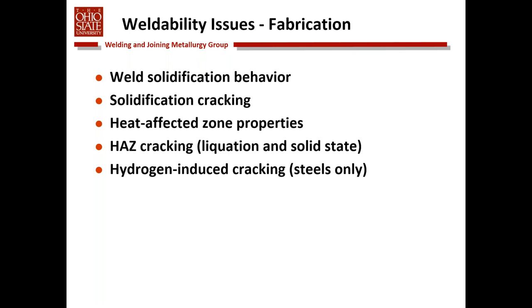So the weldability issues that we normally deal with from a fabrication standpoint are listed here. Obviously, when you take a base material and remelt it, as when you make a fusion weld, the weld resolidifies with a microstructure and often properties that are very much different than the base metal. And this can create fairly significant problems, especially with materials that are specially thermomechanically processed to produce a given grain size or precipitate distribution to give strength, ductility, toughness, etc. You now make a weld on that material and you completely destroy all that thermomechanical processing. And so dealing with the solidification behavior of welds is often very important.